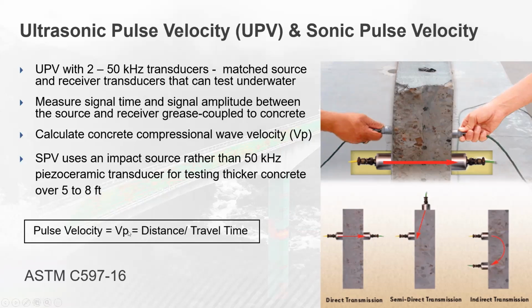Pulse velocity is simply the distance between the source and receiver transducers, which are identical. You're excited at resonance and respond at resonance. So it's distance divided by the travel time, which is measured in millionths of a second, or a microsecond. There's an ASTM standard for this as well, C597.